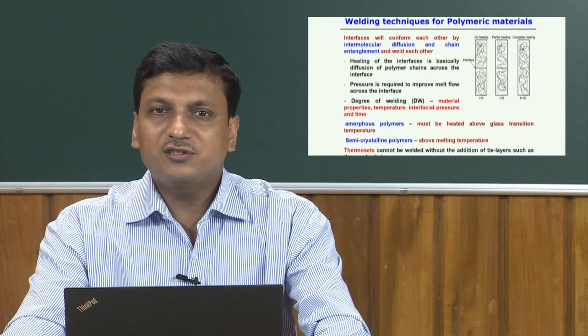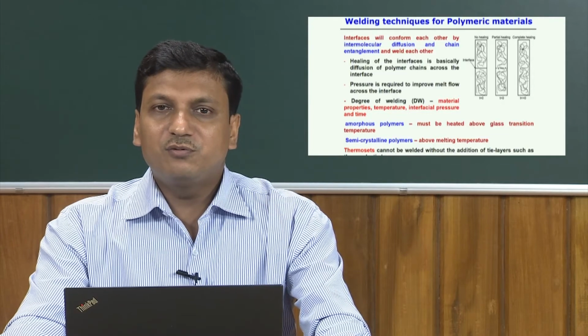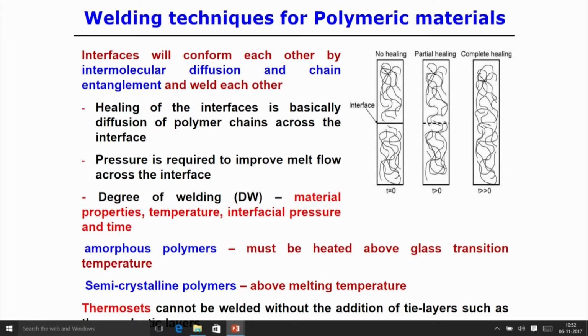Healing of the interfaces is basically due to the diffusion of the polymer chains across the interface. One important point is that diffusion of the polymeric chains happens at the interface, and the advantage is that in the case of metallic materials there may be a possibility of oxide layers. If you want good diffusion bonding between two surfaces in contact, you definitely need to remove the oxide layer, but that problem does not exist in the case of most polymeric materials. So, polymeric materials can be joined even without any surface preparation.